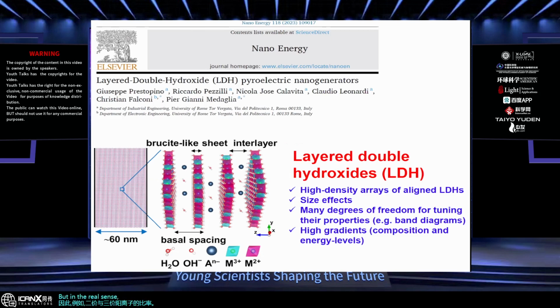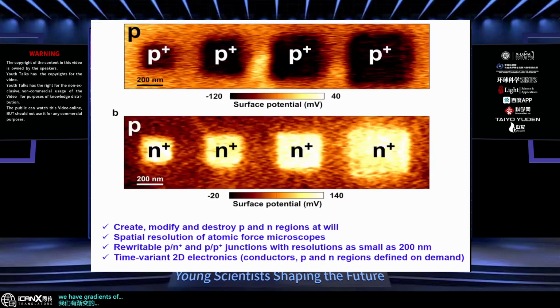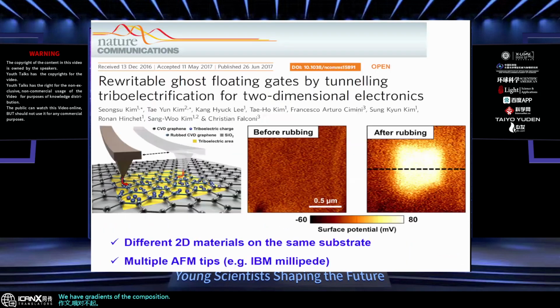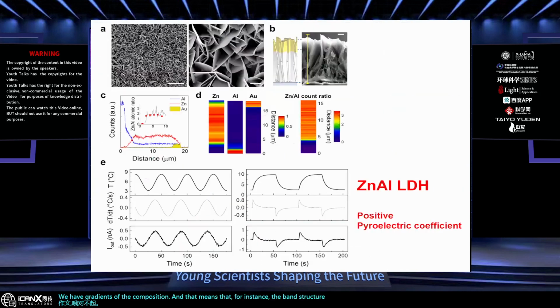But in the real structure that we designed and fabricated, we have gradients of the composition, and that means that, for instance, the band structure will depend on the position in a way that is not easy to predict. Not only the band gap, but also the minimum level of the conduction band and the top level of the valence band. They will all depend on the position, and in a way that we can measure in some way, but still we don't have all the parameters because, for instance, we don't know how much water is within the layers and the exact concentration of the anions. So there are too many parameters and a very complex system.